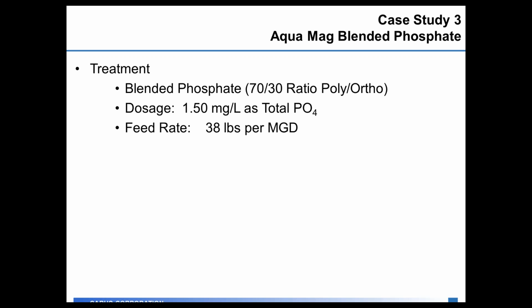So they chose, based on this water quality, they were going to feed a blended phosphate and a ratio of 70 poly to 30 ortho, and their dosage was going to be 1.5 milligrams per liter as total phosphate. And this led to a feed rate of 38 pounds per million gallons treated.